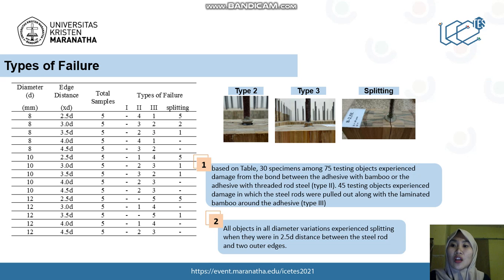This is the table of types of failure. Based on the table, 30 specimens among 75 testing objects experienced damage from the bond between the adhesive and the bamboo or the adhesive and the threaded steel rod, or damage type 2. And 45 testing objects experienced damage in which the steel rods were pulled out along with the laminated bamboo around the adhesive, damage type 3. And all the objects in all diameter variations 8 mm, 10 mm, and 12 mm experienced splitting damage when they were at 2.5 D distance between the steel rod and two outer edges.